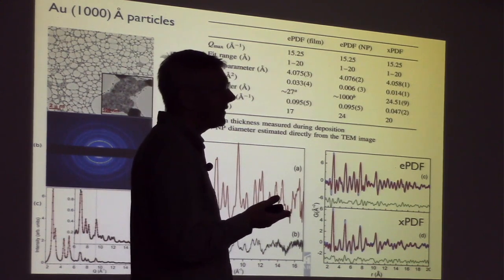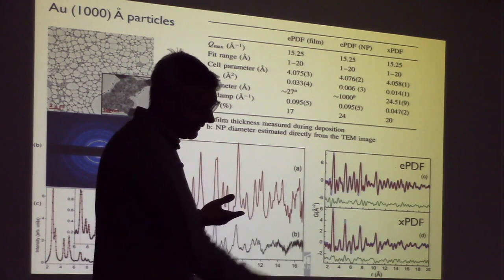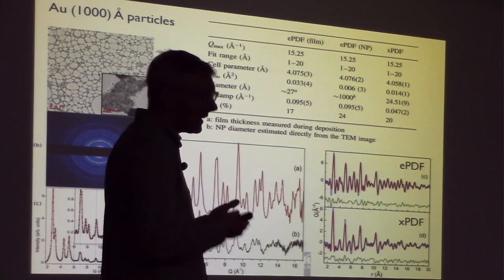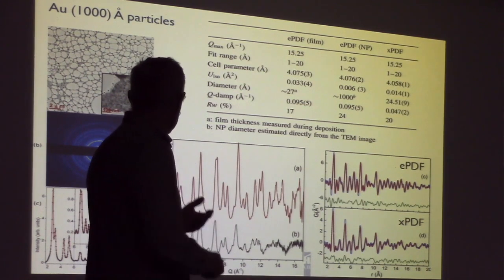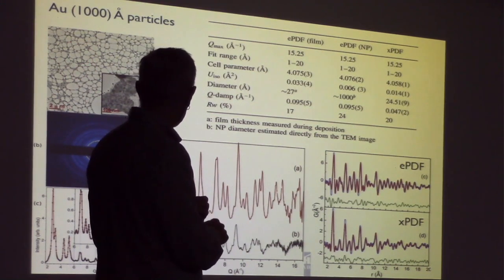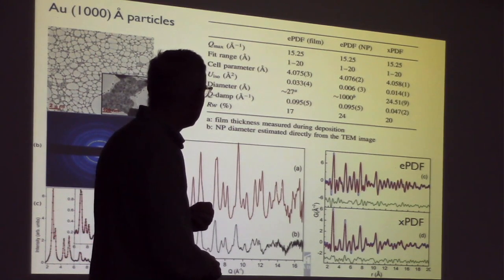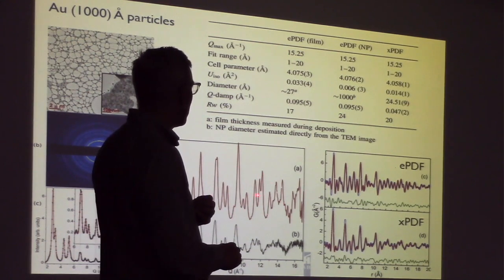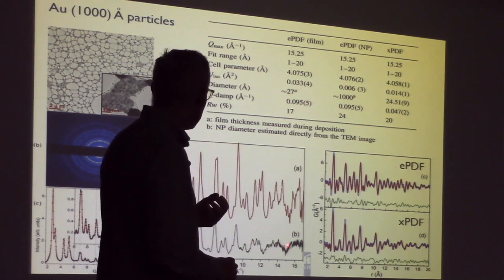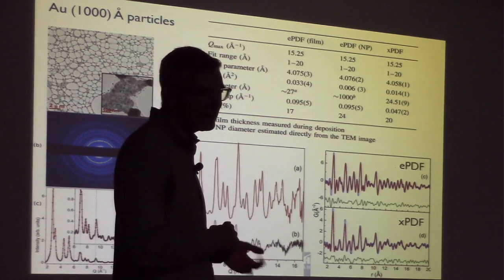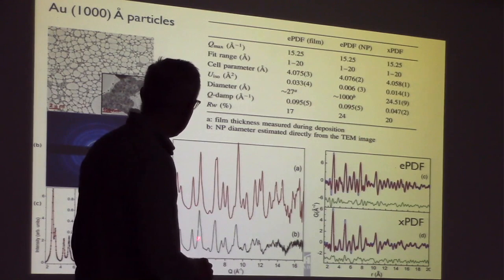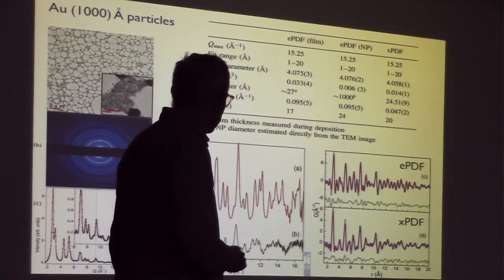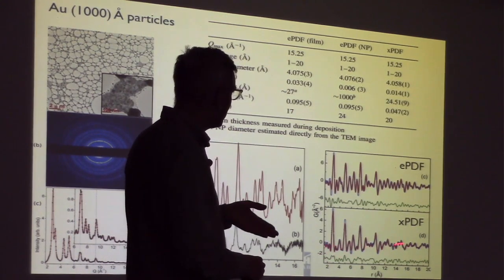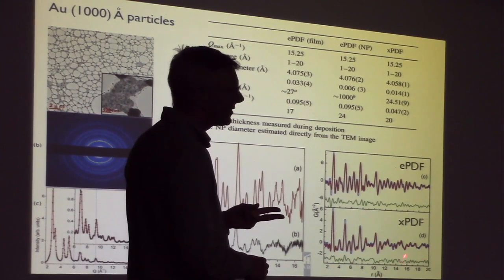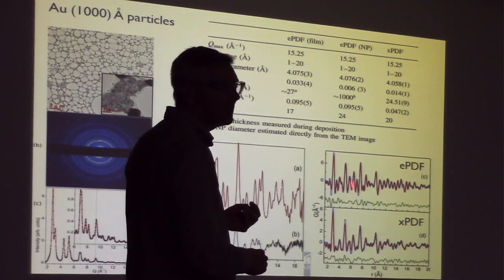But then we can change the conditions of the electron microscope. So instead of in the detector plane doing the image, we put the diffraction plane at the detector. So we collect the diffraction pattern. So this is actually a diffraction pattern from this guy. And we extract the PDF in the usual way, so we get the powder pattern here. And the red curve here is the diffraction pattern from the electron microscope for these gold nanoparticles. And this is the diffraction pattern for different gold nanoparticles measured with X-rays. We couldn't do the same measurement on the same particles, but you see that the signal is being reproduced quite well. There's a slight difference in lattice parameter. So then we Fourier transform it to get the PDF, and the PDFs are here. So this is the gold nanoparticles measured with X-rays, blue is the measured, the red is the calculated from this crystal structure model, green is the difference curve, and here it is for ePDF.